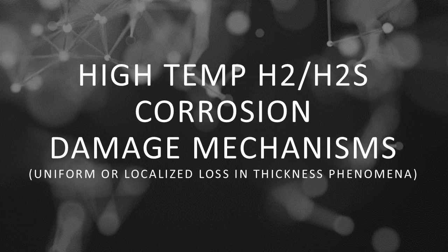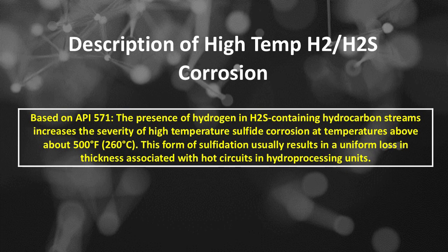High-temp hydrogen or H2 and hydrogen sulfide or H₂S corrosion damage mechanisms as a part of uniform or localized loss in thickness phenomena. Description of high-temp hydrogen or H2 and hydrogen sulfide or H₂S corrosion based on API 571. The presence of hydrogen in H₂S containing hydrocarbon streams increases the severity of high-temperature sulfide corrosion at temperatures above about 500 degrees Fahrenheit or 260 degrees Celsius.